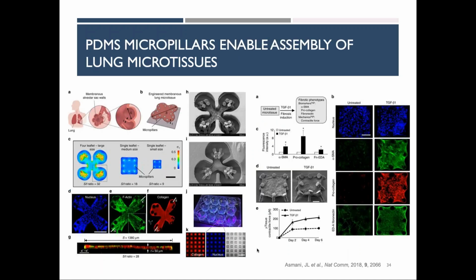One of the newer studies that I've seen out of the pulmonary field that has been really fascinating is this. They've used PDMS micropillars to enable the assembly of these tiny lung microtissues. So they created these pillar arrangements based on the size and shape of the human alveolus, and then grew fibroblasts, thin layers of fibroblasts on top of these. These cells were then treated with TGF-beta to induce fibrotic activity, and you can see an increase in alpha smooth muscle actin and procollagen, and of course fibronectin. And then you can also see that there's an increase in the contractility of these cells on these surfaces. So it's been a really fascinating way to create a thin layer of tissue that starts to mimic lung tissue, and to look at how these cells are responding when they are challenged with something that would be profibrotic.